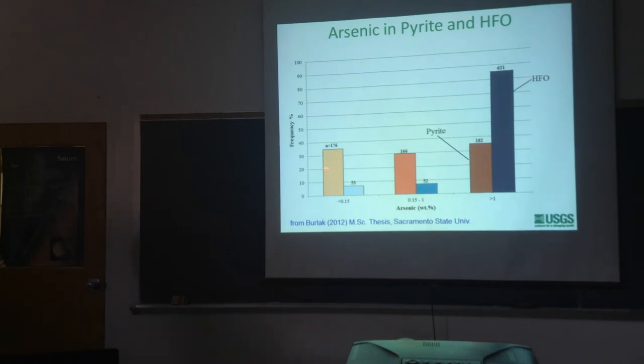And I'm going to show a map that shows these same things. This is for the overall site. You see there's about an equal amount of low, medium, and high arsenic. Here the medium is 0.15 to 1% arsenic in the pyrite. And then we consider high anything over a weight percent. And there's an equal amount with less than 0.15, which is our detection limit for arsenic in pyrite. And then the HFO was intended to be more of the stuff greater than 1%. That's a relatively small number of microprobe points that were in the medium and low range. So you can see already there's a tendency for the weathering products to be higher in arsenic than the primary material, which is kind of interesting.